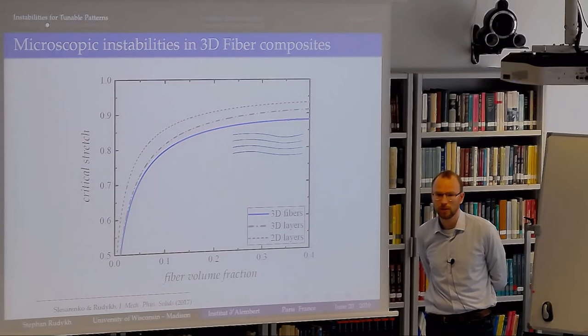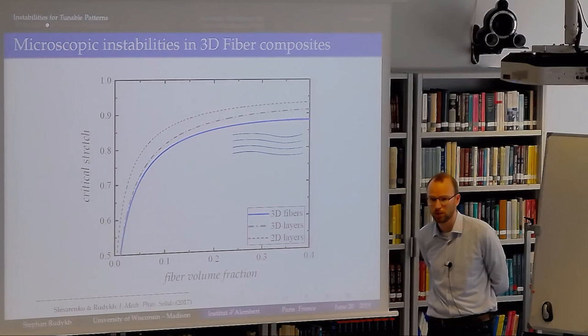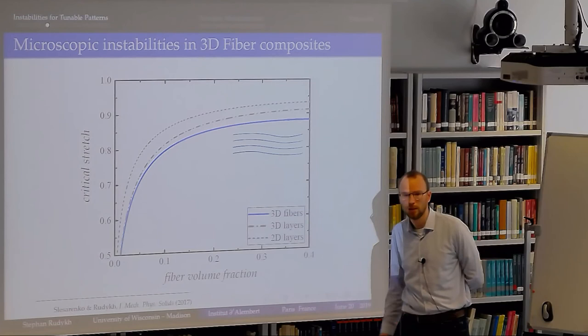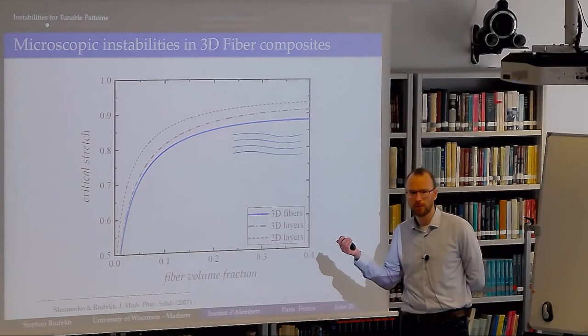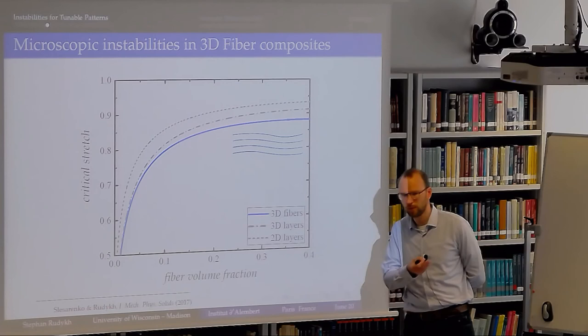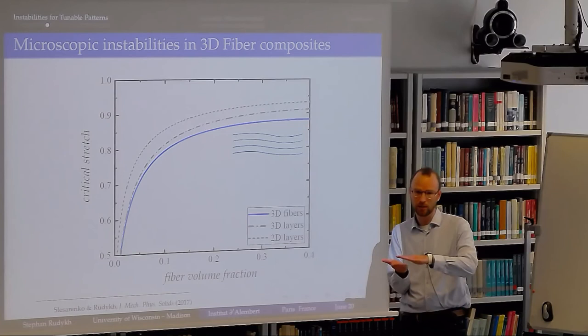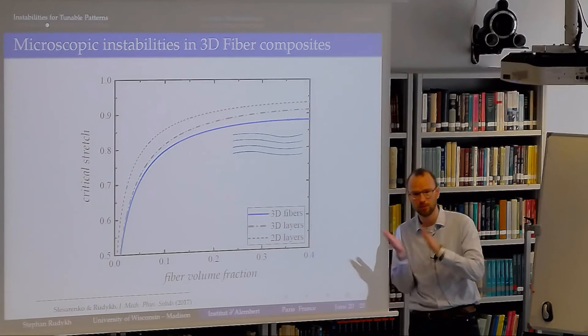We did see sometimes when we get to severe deformations that something ruptures, but not necessarily at the interface. It depends on the resolution of what we print. If you print it with a relatively small resolution, well, for us, not for people from the nano world, you basically go with one layer and you start mixing them and they cure, so it's not that you have a sharp interface to debond.